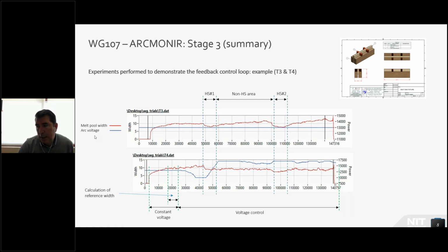So these are the curves that we obtained with the camera as it's working during the arc welding process. Here we have on top T3, which is a process that is done with constant voltage. You can see it's done with 13 volts. You can see the red line when there is no control. The red line represents the melt pool width, and you can see how the melt pool width is changing, starting here. It gets up to 10 millimeters more or less, and then it's reduced when the torch passes next to the heatsink areas.